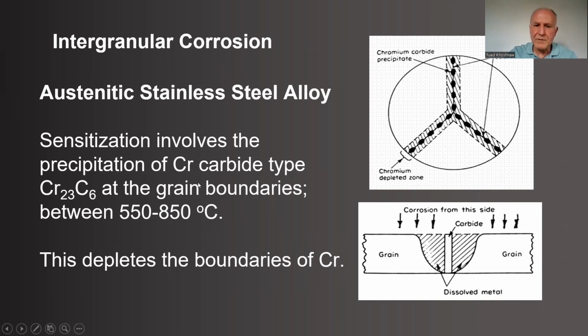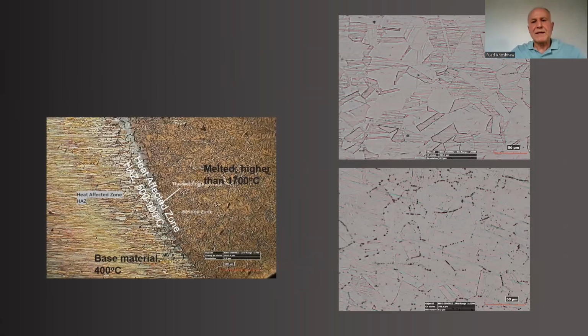chromium carbide precipitation happens. So this chromium carbide, as you see, the chromium comes from inside the grains, so from the grains onto the grain boundaries. So the chromium content inside the grains will be less than before, because it has been segregated here as chromium carbide. So some places will be depleted of chromium, some of them not. And this also, as you said, causes one type of galvanic